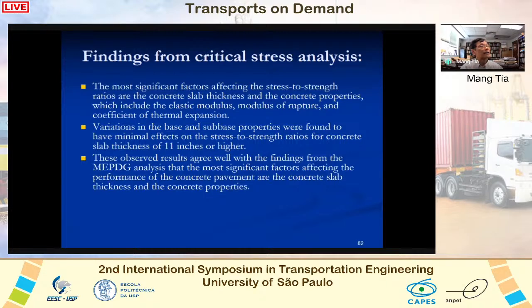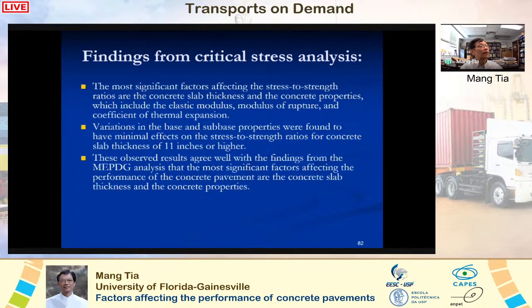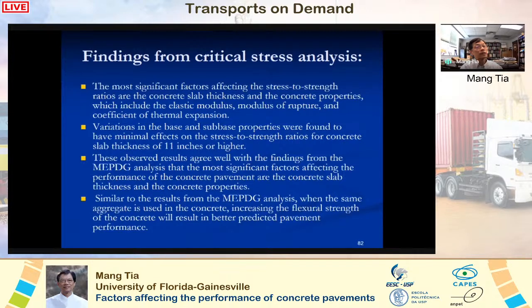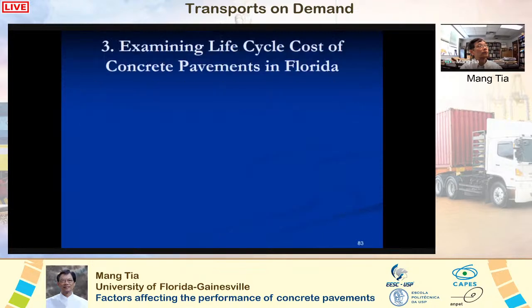These findings show that the most significant factors affecting performance of the concrete pavements are the concrete slab thickness and the concrete properties. And similar to the results of the MEPDG analysis, when the same aggregate is used in the concrete, increasing the flexural strength of the concrete will result in better predicted pavement performance.